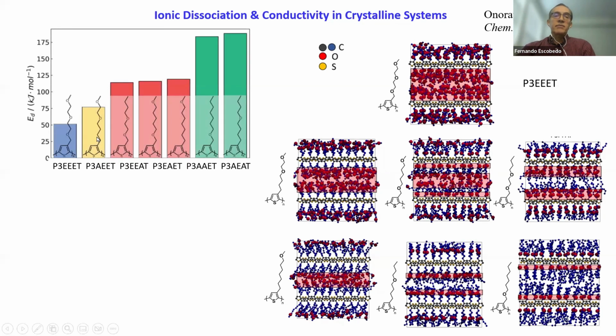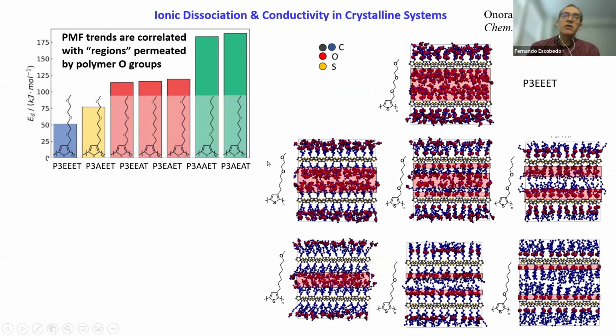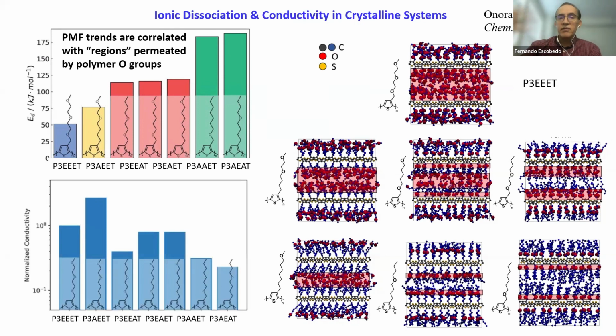We look at these free energy barriers for these different materials. The smallest one corresponds to this chemistry, which is the standard P3EEET with the 3 oxygens. And the barriers become larger once you have smaller permeated regions by oxygen groups. So that in some ways was to be expected. But if now you look at the actual ionic conductivity, which is normalized so that 1 corresponds to the base system, which is the first one, what you find is more nuanced.